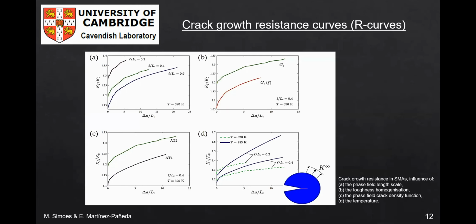So we use this boundary layer formulation to apply a remote load as characterized by the remote stress intensity factor K_I, and to compute the crack extension delta a using our phase field formulation. This gives us crack growth resistance curves. The results shown here analyze the influence of, in A, the phase field length scale, in B, the toughness definition, in C, the crack density function, and in D, the temperature. In all cases, the model predicts a toughening effect, a raising of the R curve, that is associated with the energy dissipation due to phase transformation, as observed in the experiments.